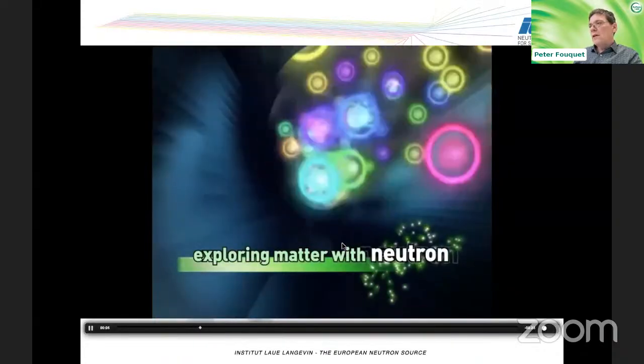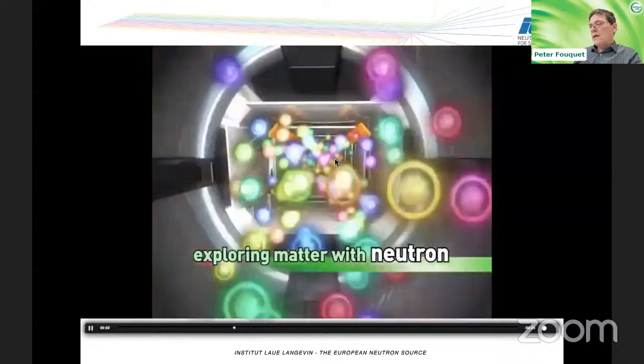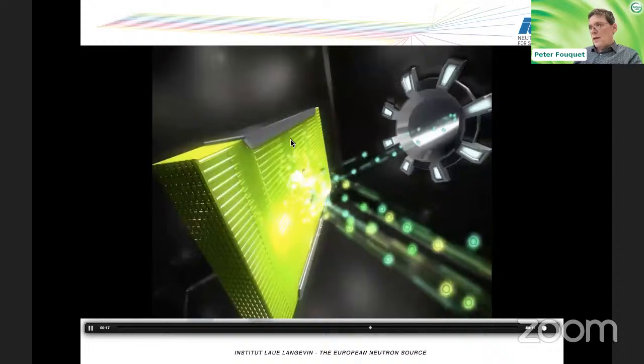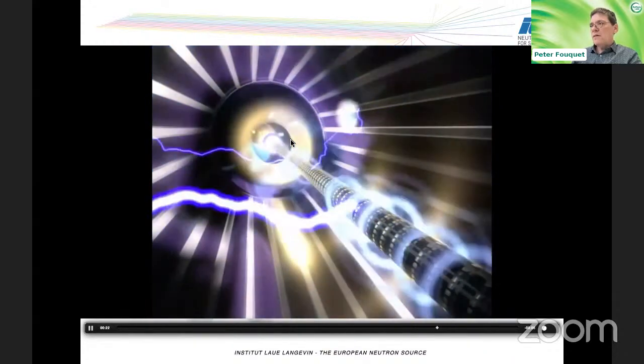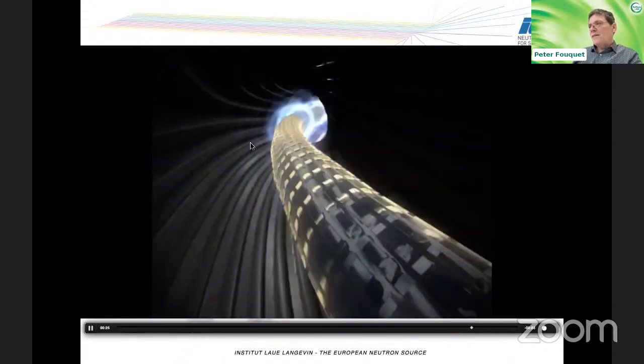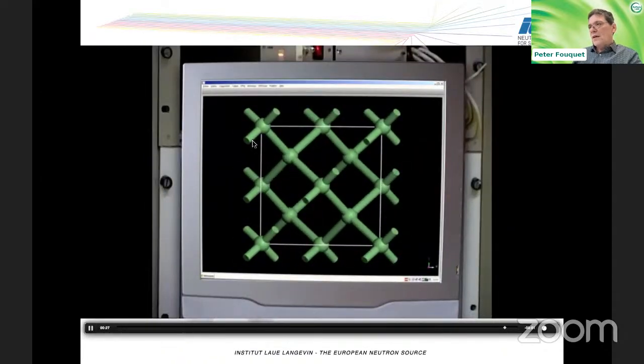I show you in a little film here how this is done. So the neutrons come out of the reactor. They go into the guides after they have been in the energy moderator. Then they come to an energy-selecting monochromator, then the sample, then an analyzer, and then they are detected, artistically shown here. And with that, you can get information about how these samples move in our case.